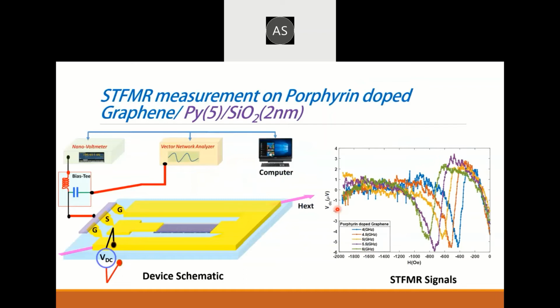So now we started measurement. So we have set up the experiments in this form. We have actually used the vector network analyzer as a source, and a nanovoltmeter for detecting the signal with the bias. And along with this STFMR, what we did is we have also applied a backgate voltage, as I have shown for the GFET device measurement. So we have applied this backgate voltage, and we have measured this STFMR spectra with respect to VDC. The STFMR spectra that you see on the right is basically what we have obtained with no gate voltage applied. So it's a simple STFMR spectra.